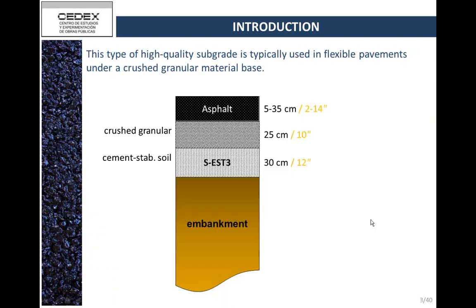So, for this type of subgrade, you can see here the subgrade, which is this cement-stabilized layer on top of the soil. We typically use these subgrades in the main highways. In fact, when you build a new highway, you are required to use this type of subgrade. And the typical situation is that we use this subgrade with a crushed granular material as the base of the pavement and then an asphalt layer. This asphalt layer depends on the level of traffic, and we can go from 5 centimeters, which is 2 inches, to 35 centimeters, which is 14 inches. For the highest levels of traffic, we use a very thick pavement. This could be the situation of this layer in a typical pavement in Spain. So traffic is always a bit far from this layer.